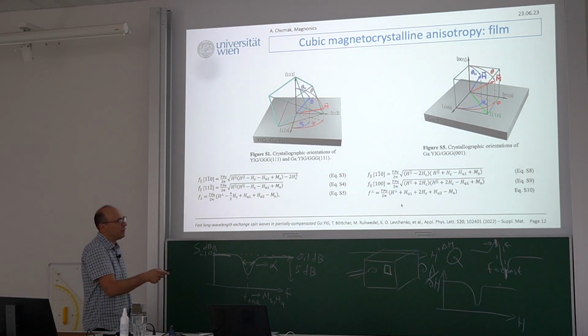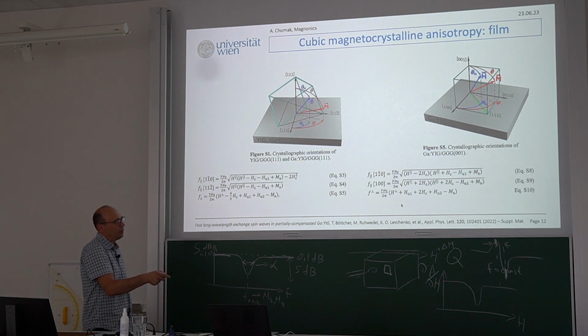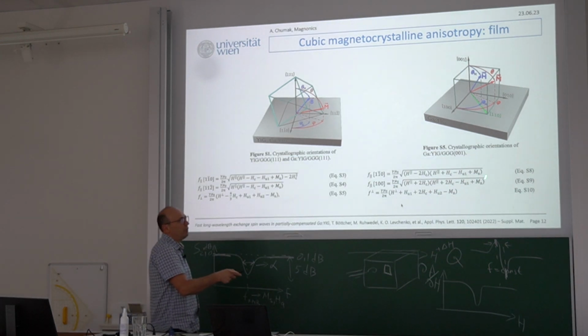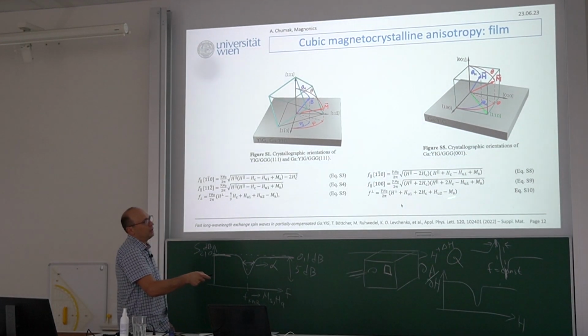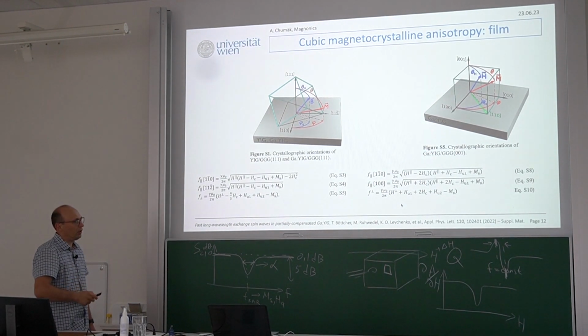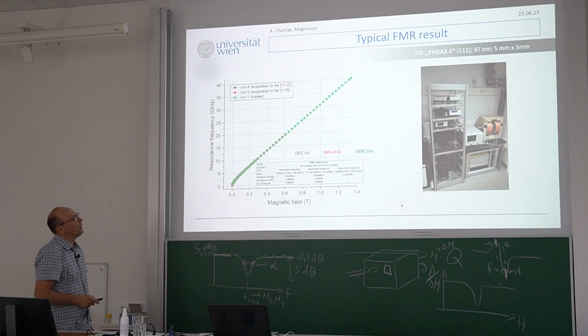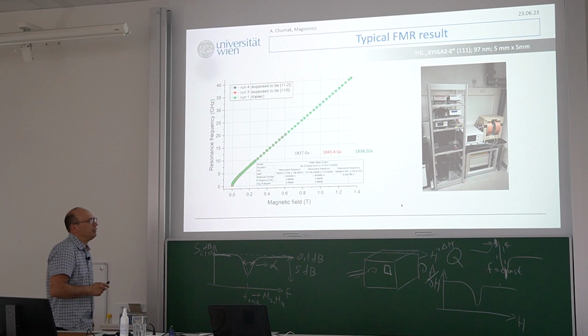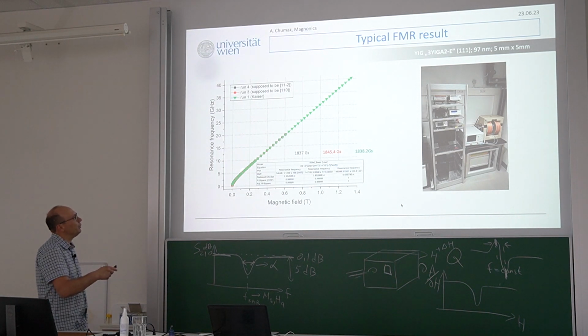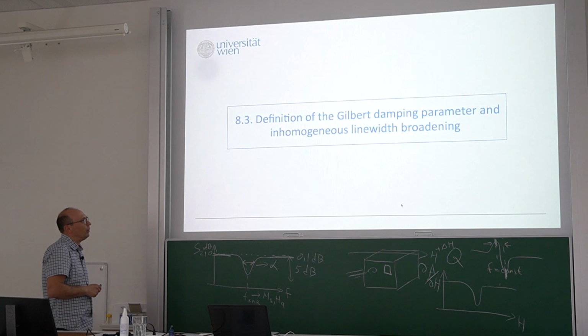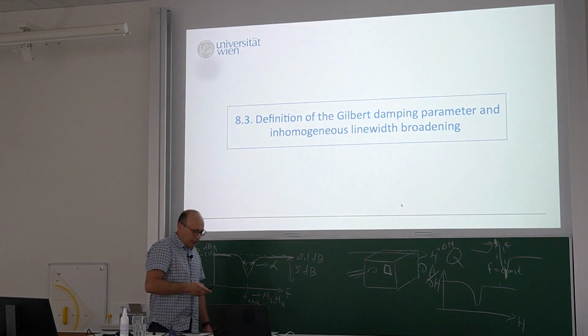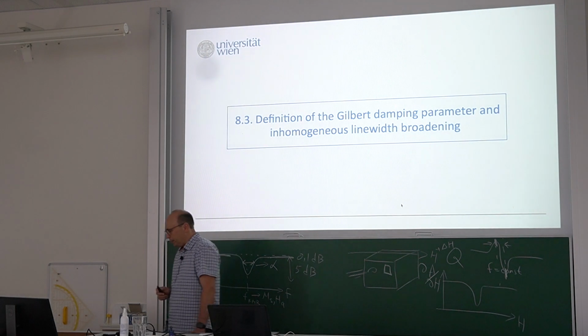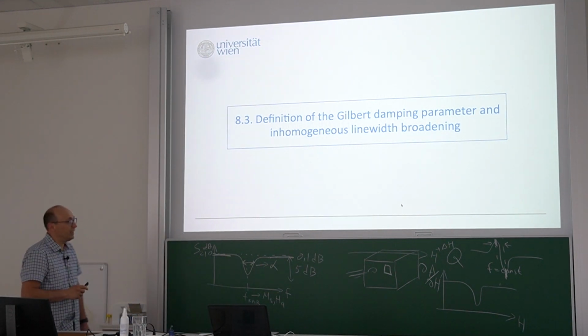and maybe you need to measure for several different angles. But what you will get out of there, first of all, is magnetization. Yeah, it's large components of this H parallel or H perpendicular. It's applied magnetic field, and MS is usually your unknown. But in addition, of course, you have these smaller components from anisotropy. So you can get then magnetization in this case, if, for example, you ignore crystallographic anisotropy, and you will have such a curve which you can easily fit in Origin, for example. The story might be a bit more complicated if you want to get the Gilbert damping term.